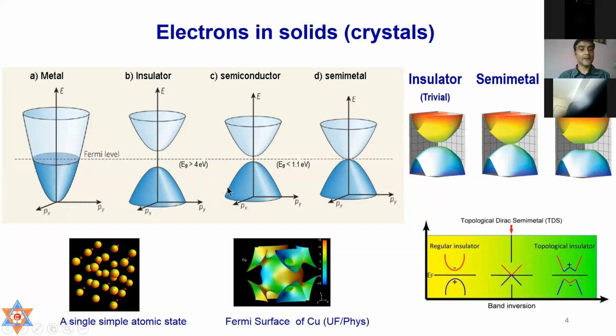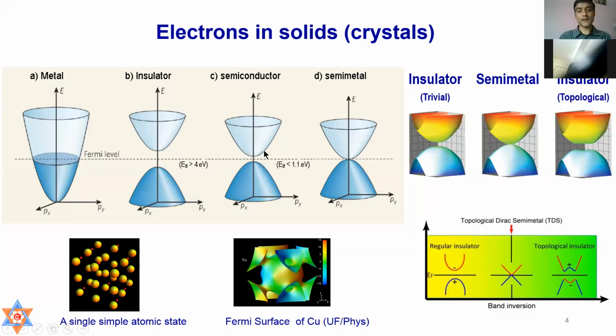And then the semiconductors also have a gap, but the size of the gap is really very small. Depending on the material, whether it is an element, for instance silicon or germanium, the gap size will be somewhere between 1.1 eV and 0.6 eV at room temperature. If it is in compound form, the gap may be still very small or large as well.